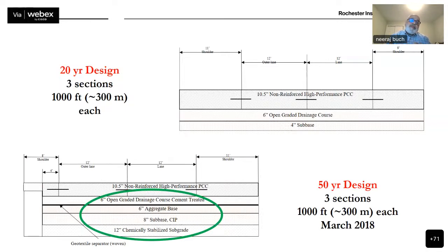Now, if you look at the 20-year design and the 50-year design cross sections, the slab thickness is exactly the same. Michigan DOT chose to design the same slab thickness for both the concrete pavements. So the slab thicknesses were 10.5 inches, which is approximately 275 millimeters of thickness. But there was significant difference in the foundation layers.